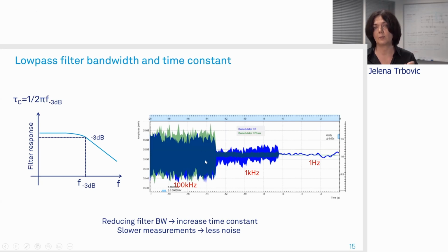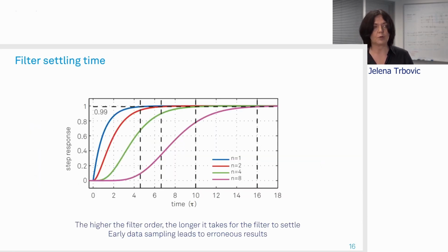This means that the time constant is very short. And further, if we continue reducing the bandwidth or increasing the time constant, we see less and less noise. However, the price that we have to pay because the time constant is getting longer is that we will also be measuring longer. And for this to be even more clear, we can look at how the filters that are necessary for these measurements are settled.